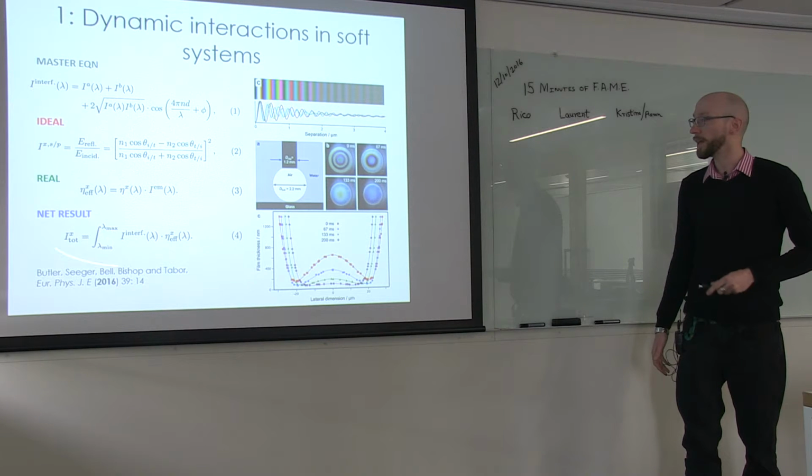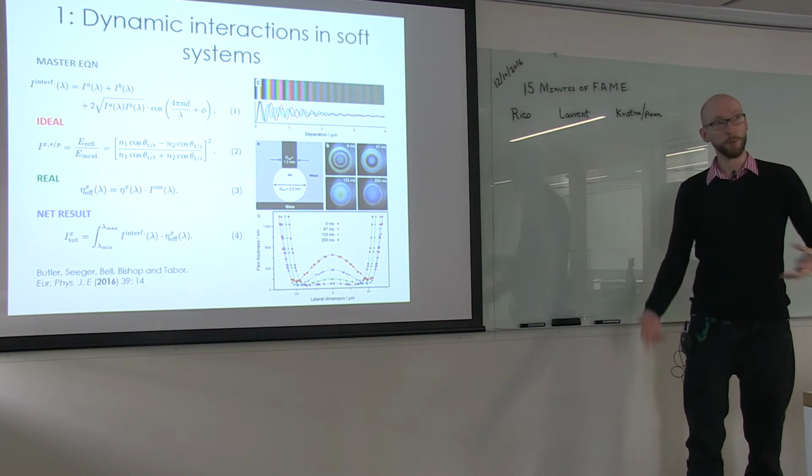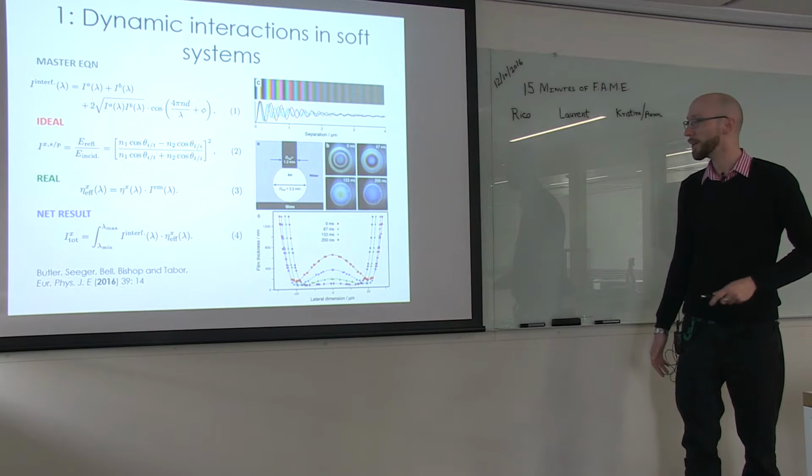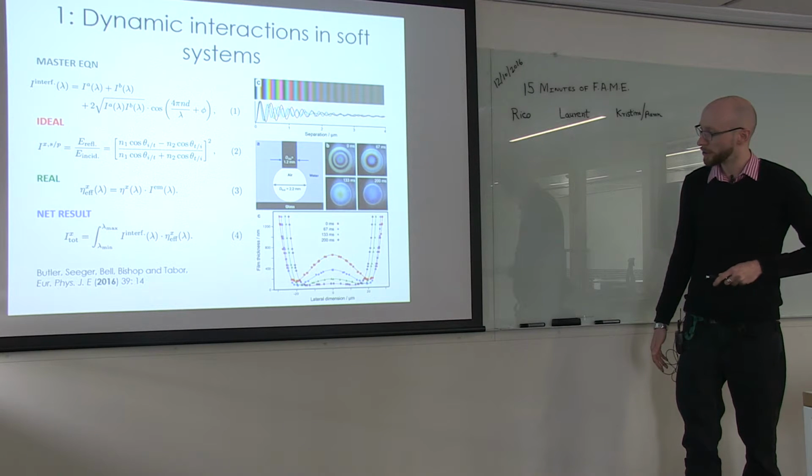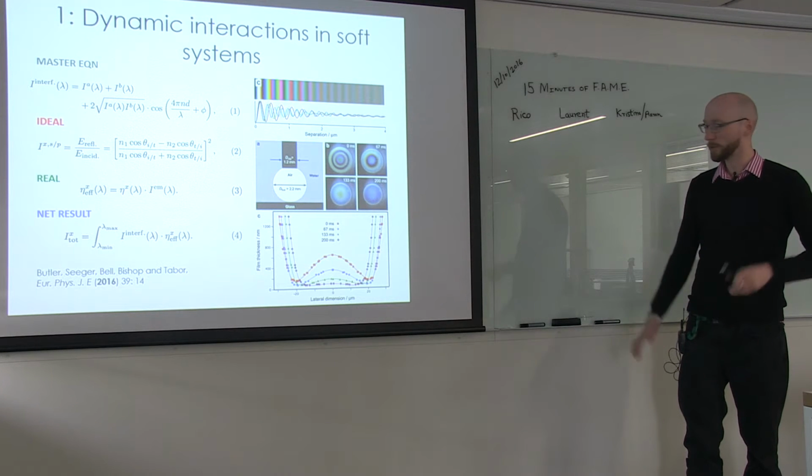And the net result of that is that you can solve colour interferometry much more simply than was previously believed. And we published this year. If you use this, you can extract the film profile. So we know this is the shape of the bubble. Obviously, it's an exaggerated y-axis here. We've got nanometers in this dimension and microns in this dimension. This is the profile of the bubble as it interacts with the surface.